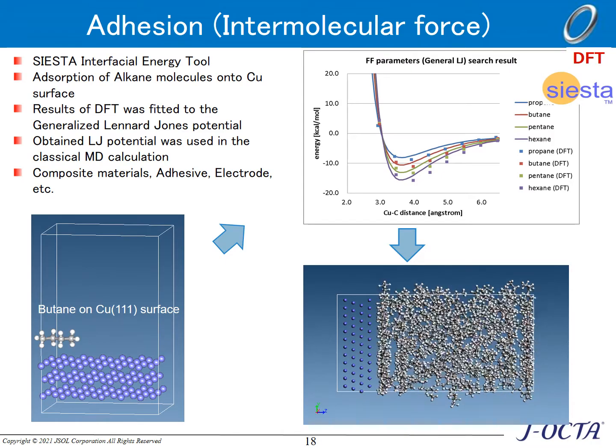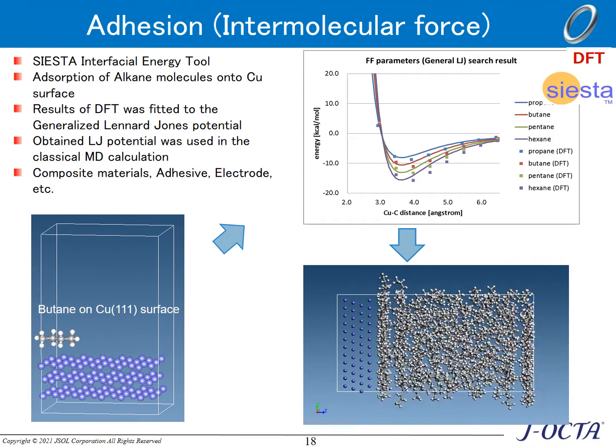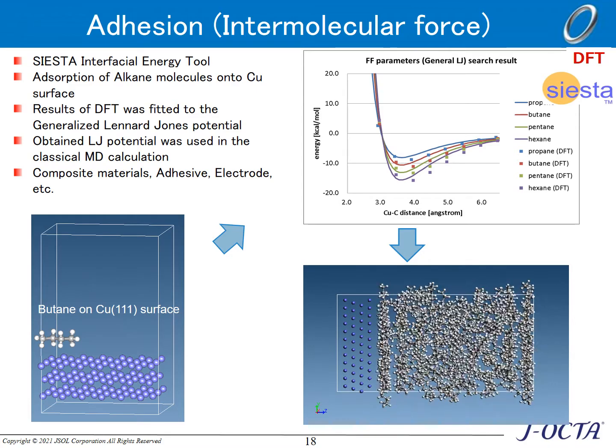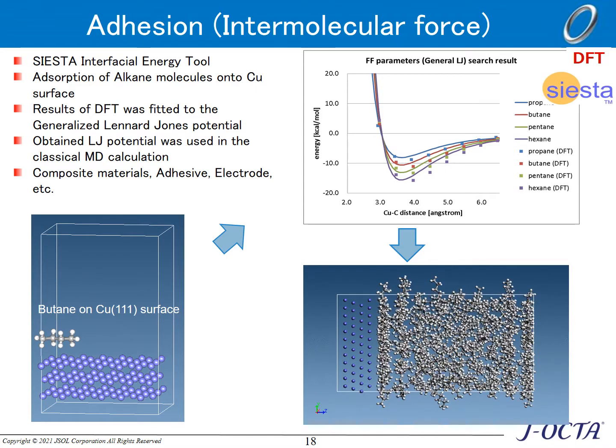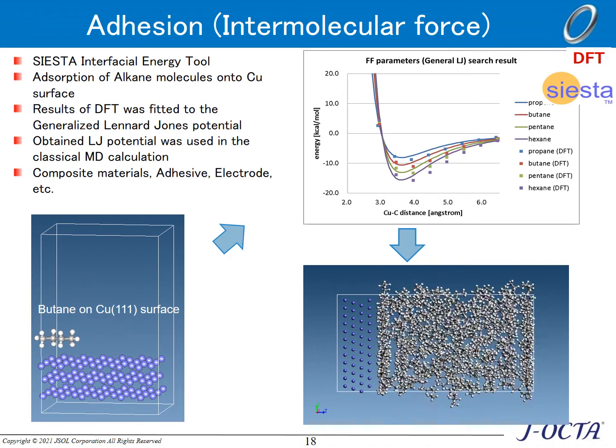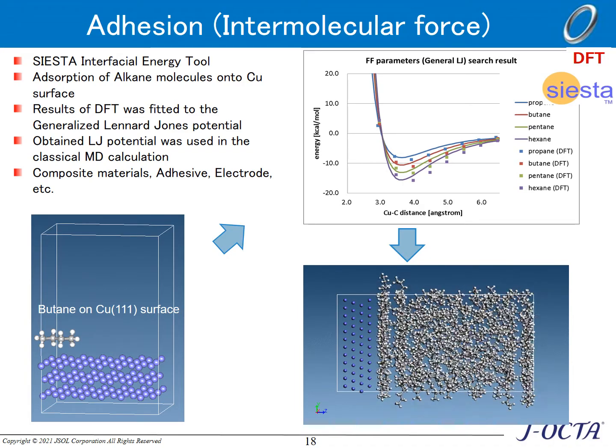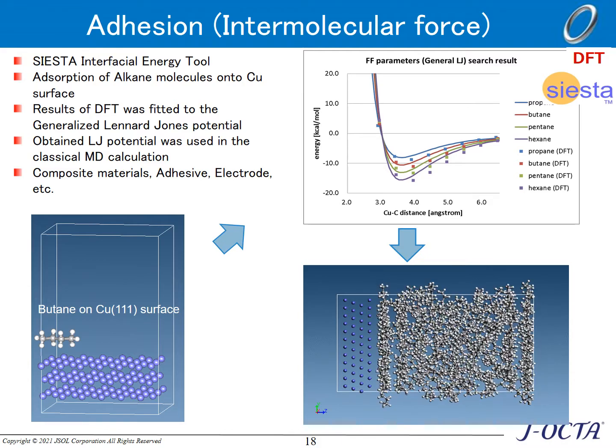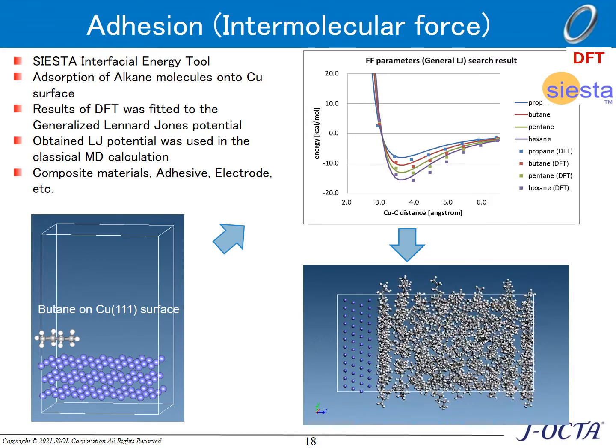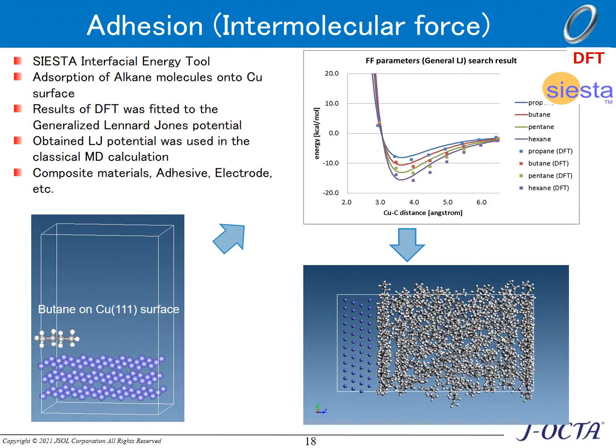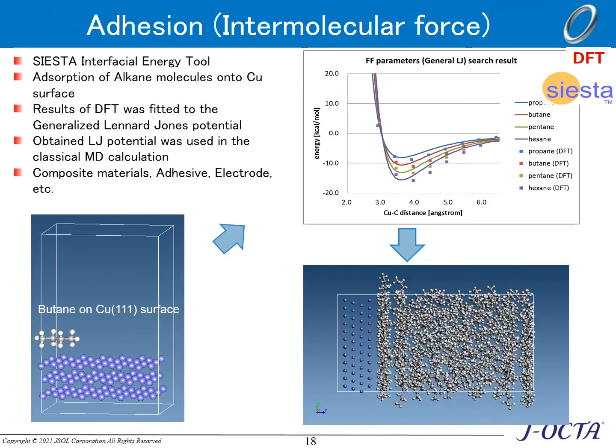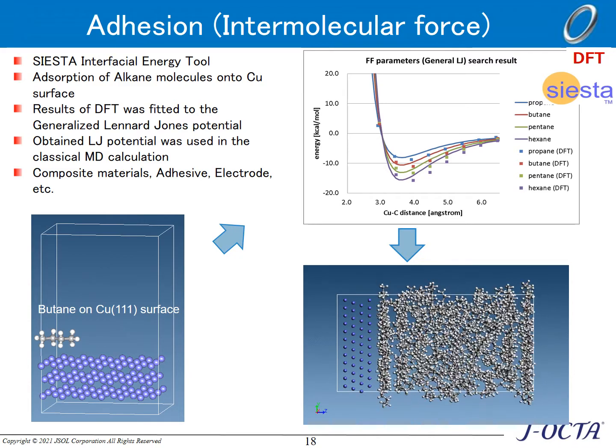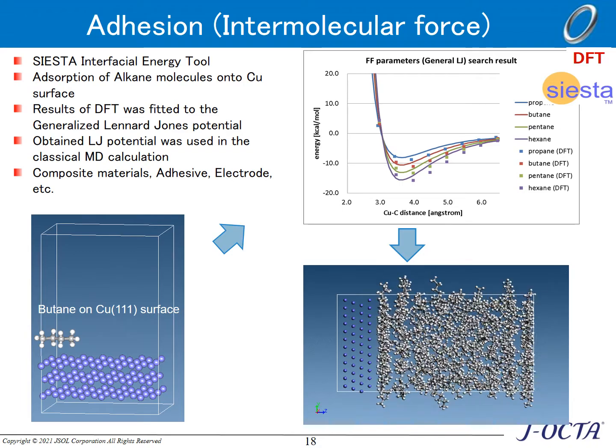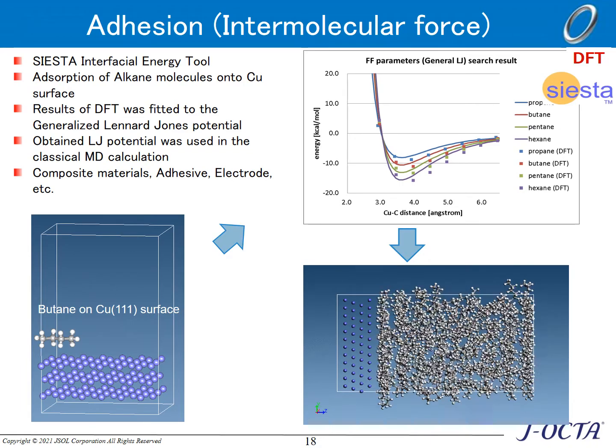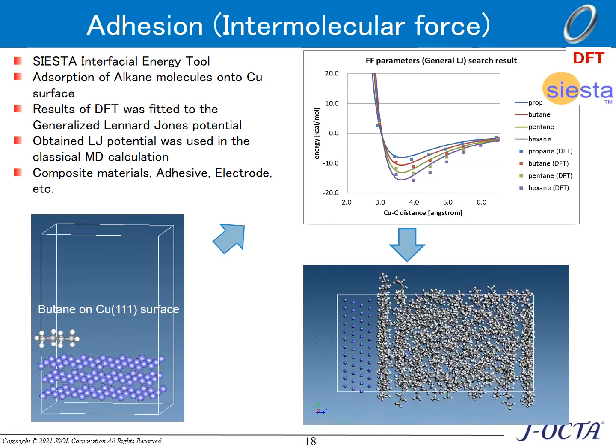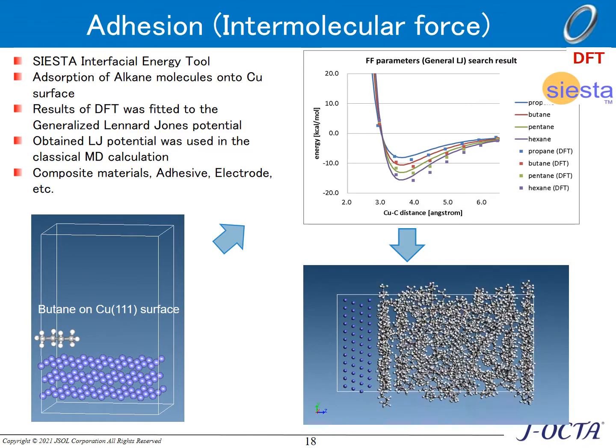Following the previous slide, this slide also uses J-OCTA to calculate the adsorption behavior of organic molecules on inorganic crystals. The lower left figure shows butane adsorption on a copper surface. The upper right graph shows the adsorption energies of butane, pentane, and hexane on the copper surface. The horizontal axis is the distance from the surface and the vertical axis is the energy. The dots are the DFT results, and the solid line is a graph drawn using force field parameters that were determined to reproduce the results.